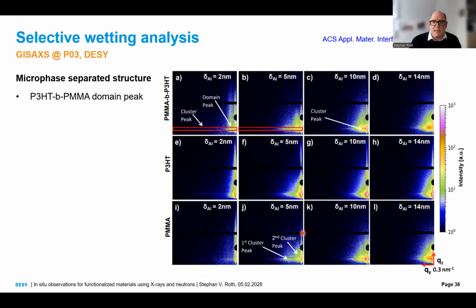And this is also what we see in situ. We start here with these images. You see here for the diblock peak, for the individual P3HT layer, and for the polymethyl methacrylate, you see the growth of aluminum. You see this looks completely different. Now you see here aluminum on PMMA gives here only very small signal, and here a broad side signal, and here you see a very nice height growth. And on the diblock copolymer, you see here a peak which stems from the lamellar structure of the diblock copolymers and the cluster peak. And this cluster peak resembles very much the peak you find on the P3HT, confirming what we saw in the AFM, that the aluminum grows preferentially on the P3HT.